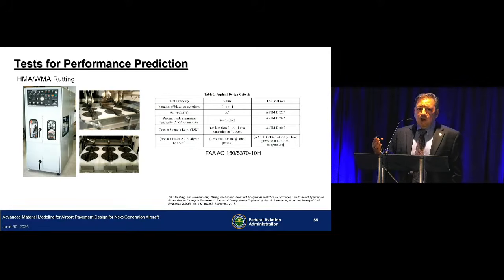John Rushing from ERDC visited our facility, and he did a significant amount of testing on his mixes as part of his PhD dissertation. And we developed a criteria that if a mix experiences less than 10 millimeters of rutting at 4000 passes at 64 degrees, it is good enough to go on an airport and should not suffer significant rutting issues.